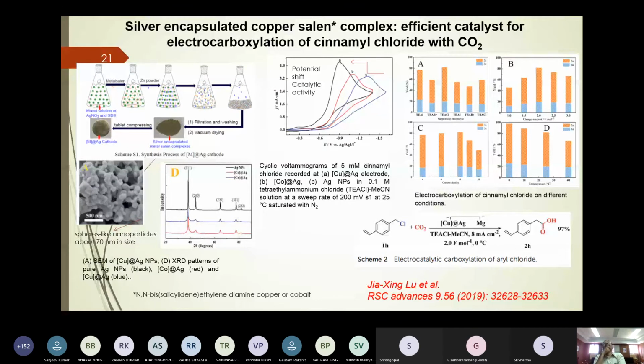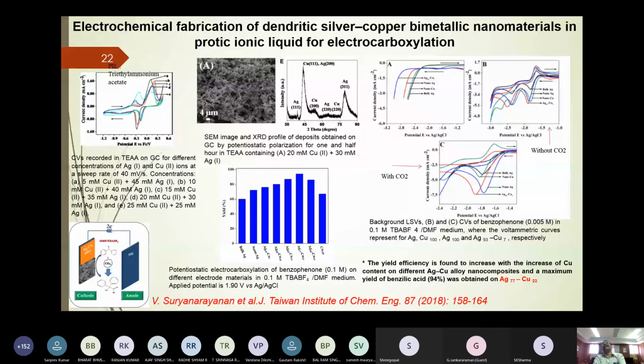Now I am moving to the next slide, where we have silver copper binary alloys obtained in an ionic liquid medium. CV shows how the copper silver alloy behaves, in voltammetry for different silver copper alloys of different compositions, for example from 5 millimolar copper to 45 millimolar copper. Then the SEM image shows the morphological characteristics of the silver copper alloys, followed by XRD, which confirms the formation of copper silver.